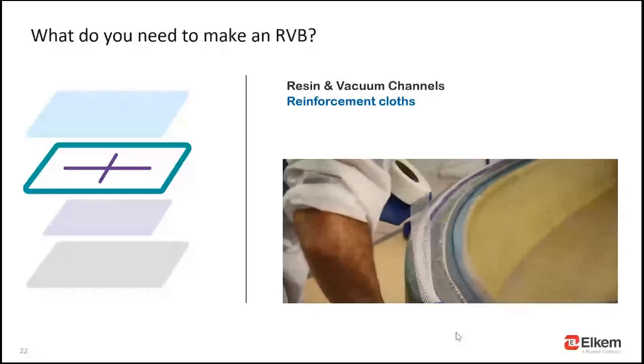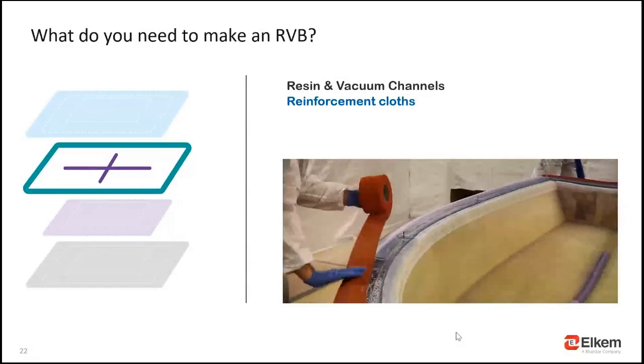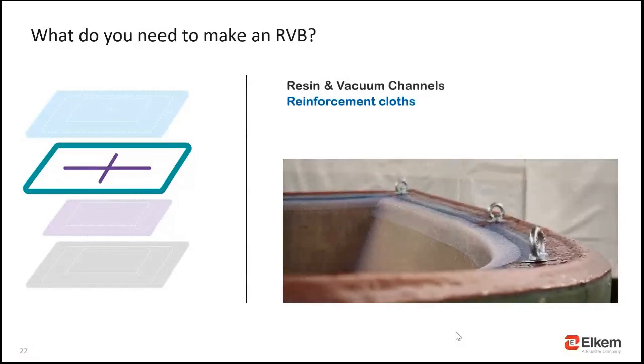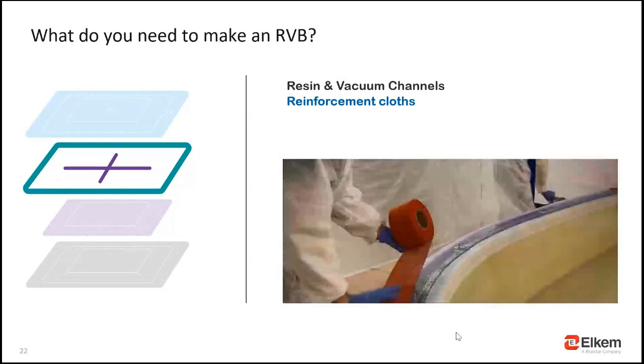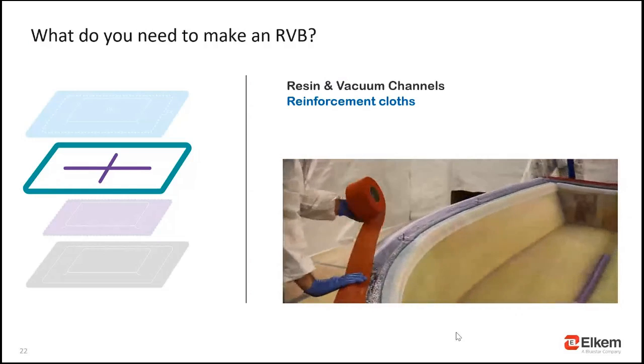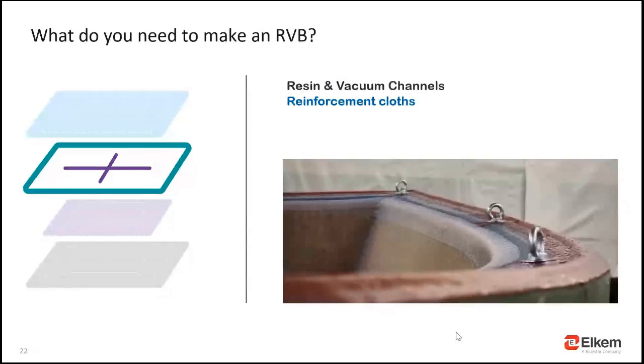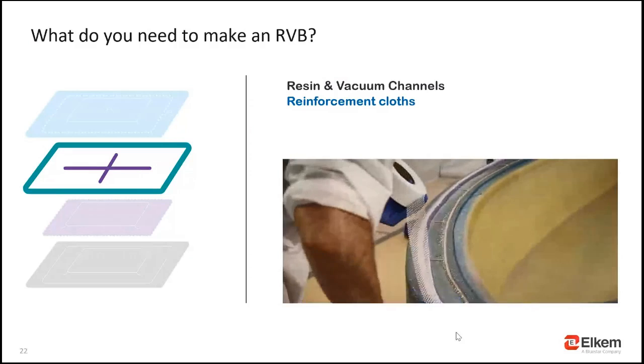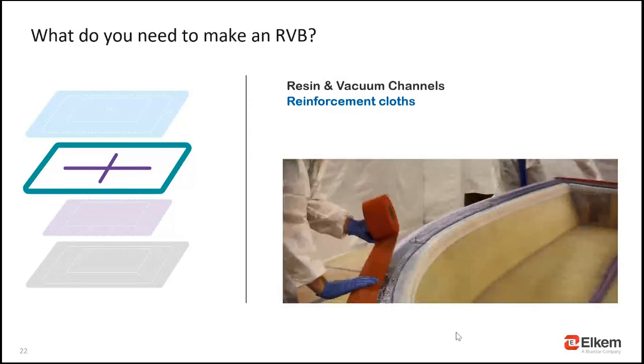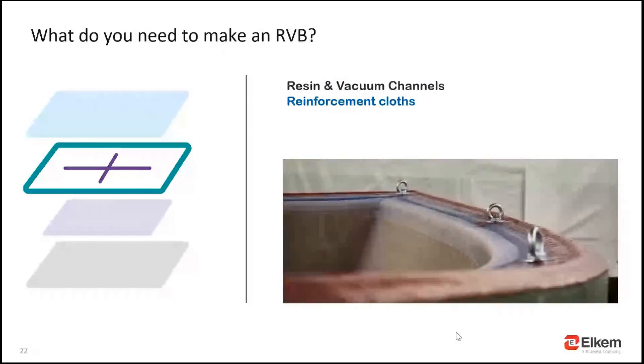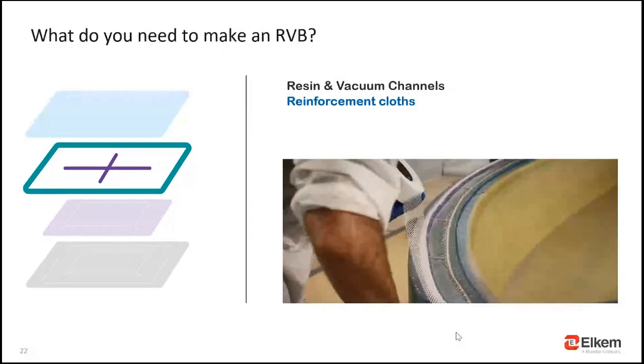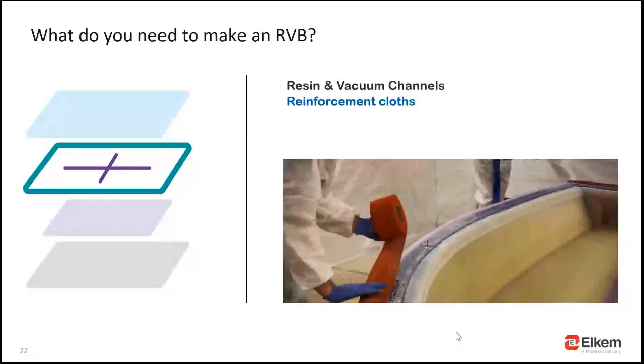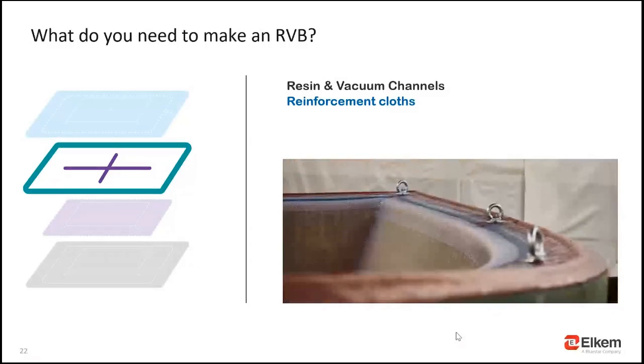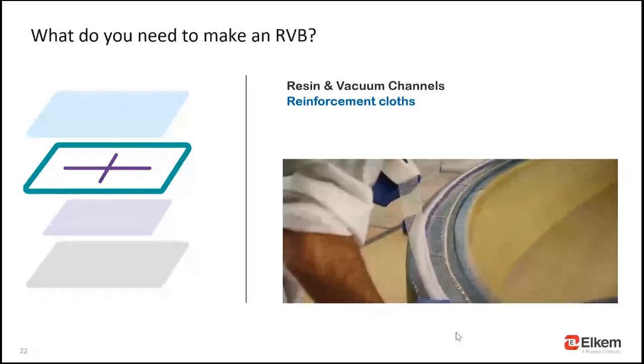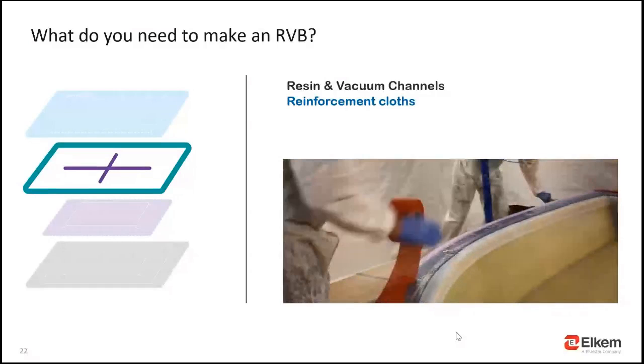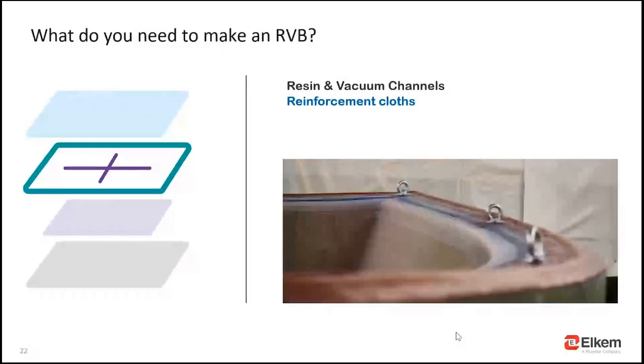Elkem RTV silicones can have a high elongation performance, reaching up to 500% of elongation. This is an important property on the demolding and prevents tearing. On the other hand, the mold borders and channels have a better performance with a more rigid profile. This guarantees that the positioning will be maintained and the setup time will not be augmented. Now, regarding the channels, rigidity will prevent them from collapsing, keeping them open for the resin to flow. To increase rigidity, reinforcement cloths are positioned in the silicone matrix, between the layers of silicone. This cloth will fortify the selected areas, keeping the high elongation only where it's the most important.